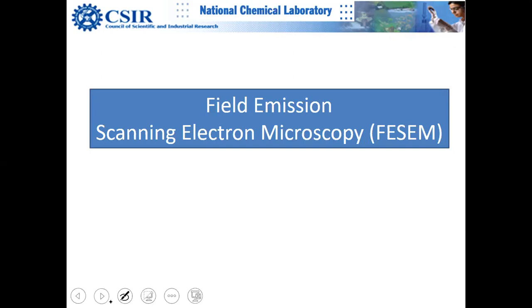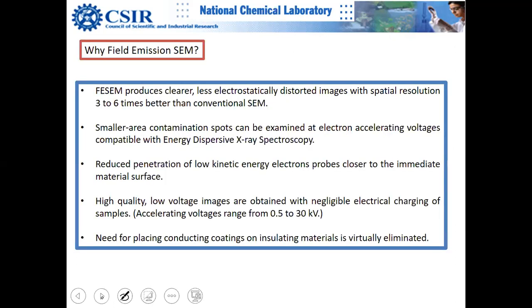Field emission is becoming the mainstay and is popular because of higher resolution, much higher quality, and you can afford to use lower voltage with less charging. Less charging means better image clarity because sample charging degrades image quality.